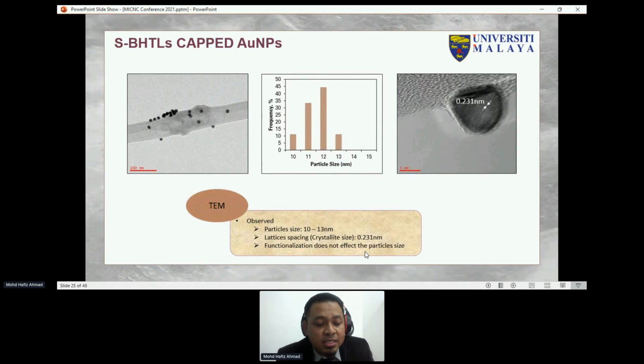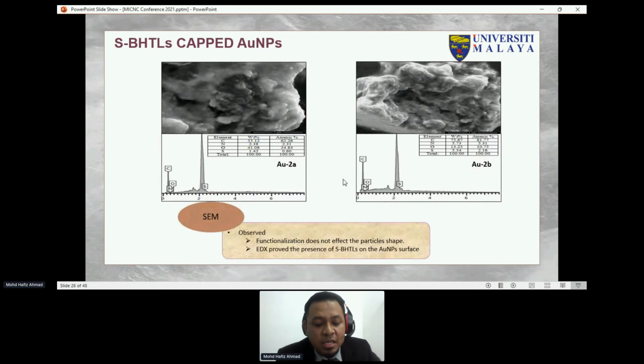And next, the TEM image shows that the particle size still remains the same after functionalization. As we can see here, the size distribution of the nanoparticles is still in the range of 10 to 13 nanometers. The image also shows the functionalization of ligands on the gold surface does not affect the particle shape. The shape still remains nanosphere. Then, the EDX analysis proved the presence of ligands on the surface of the gold nanoparticles. It showed the presence of all elements contained in the ligand.